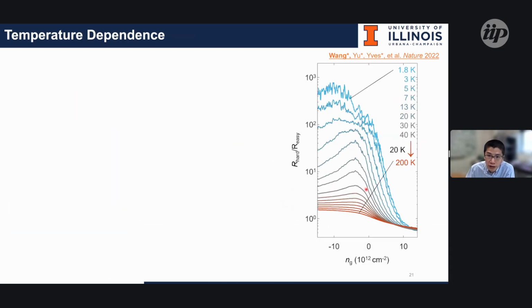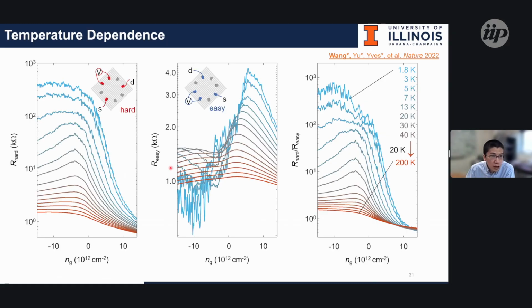With this, we can further confirm the transport property dependence. With increasing temperature, the anisotropy will drop. Along the hard direction, the resistance keeps dropping, while along the easy direction, the resistance barely changes, mostly maintained at around 1 to 2 kilo ohm. So the anisotropy mostly comes from the enhancement of resistance along the hard direction.